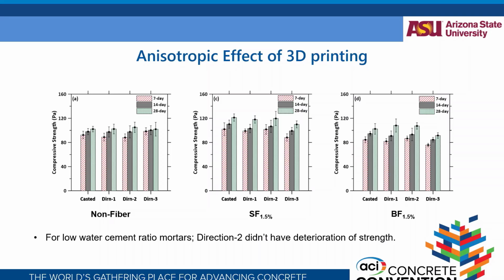If you go to a higher layer height, most probably there will be more significant differences. But again, to keep every result comparable, we are doing it at layer height 10. So we see that direction 2 does not have as much effect, which most probably will be useful for creation of wall sections, compared to the normal strength mixes.